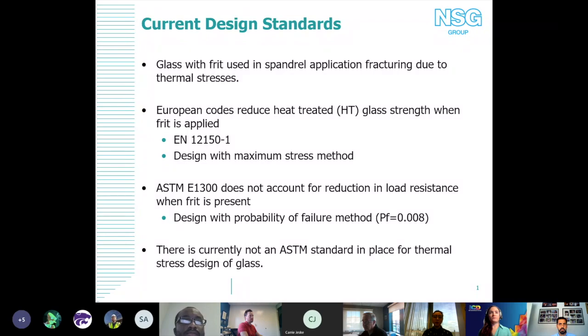And so digging a little more into the research, you see that the European codes actually currently reduce the strength of heat treated glass once you apply a frit. There are some differences between European codes and US codes that make us being able to do this a little more difficult. In European codes, they're designing their glass using a maximum stress method. So they assume that the glass always fractures wherever the maximum stress in the glass is. Once you apply frit, they add, I believe, a 30% reduction to the strength of glass.